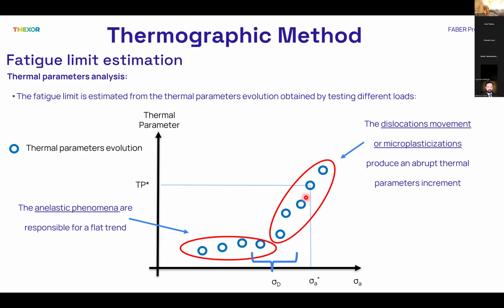No, in general one specimen is enough, because generally the number of points in the part where there is an abrupt thermal parameter increment is not more than 2 or 3 points. So this is enough. Okay, that's the important point.